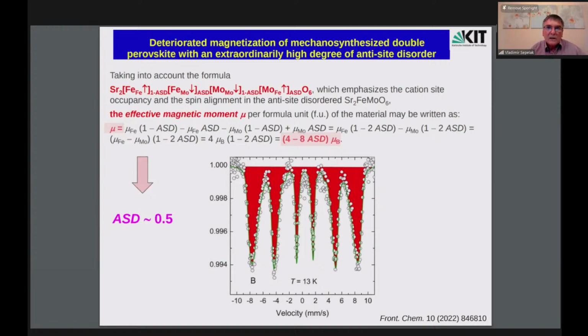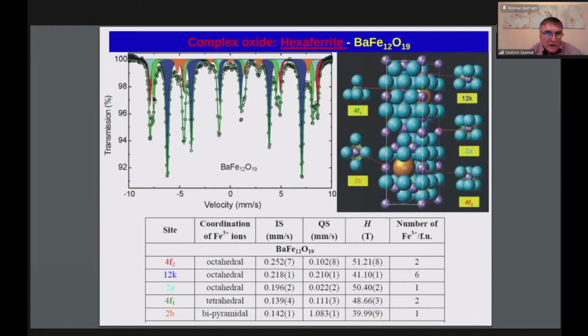I think the most complex and most difficult cases are complex oxides with many sublattices, as is the case of hexaferrites. We have synthesized them using mechanochemistry, and you see the bulk material, the Mössbauer spectrum of barium hexaferrite. We have five subspectra corresponding to various coordinations of iron in the structure: three octahedral sites, one tetrahedral, and one bipyramidal sublattice. From the intensity of these subspectra, we can calculate the number of these ions per formula unit in the bulk material and in the mechanosynthesized material too.